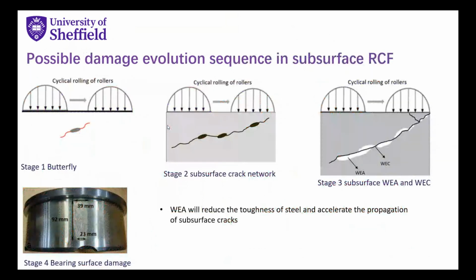So here's the quick conclusion here. In stage 1, we have butterflies, and the cracks may propagate and connect with each other, forming the subsurface crack network. Then we may have some WEA and WEC, which accelerate the crack propagation. And the final stage is the surface spalling, or the premature failure of the bearing.